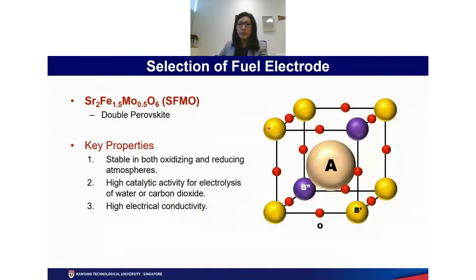So, the material of selection is based on SFMO, strontium iron molybdenum oxide, and it has a double perovskite structure. Its key advantage is that it's very stable in both oxidizing and reducing atmospheres. So now the most common electrode for solid oxide electrolyzer is still the nickel YSZ, but it's not the most stable material in this environment.